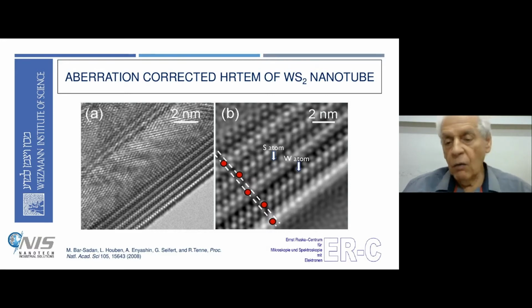So now we can study their structure to the finest detail, and we can see that indeed these are tungsten disulfide nanotubes. You first see the tubular structure, and you see how nicely and perfectly these layers are stacked together to form this tubular shape.